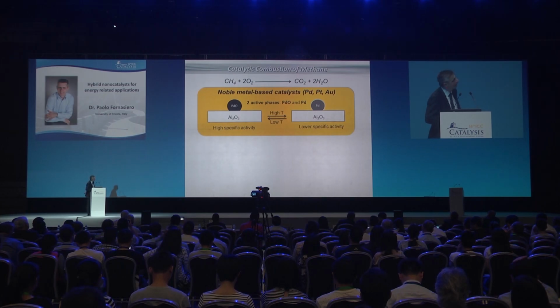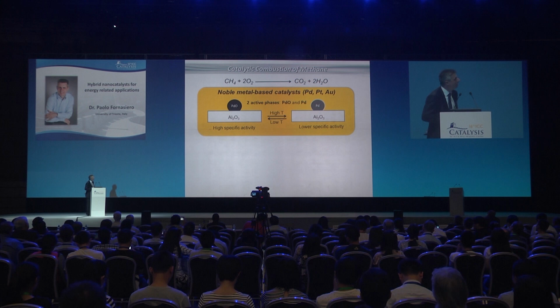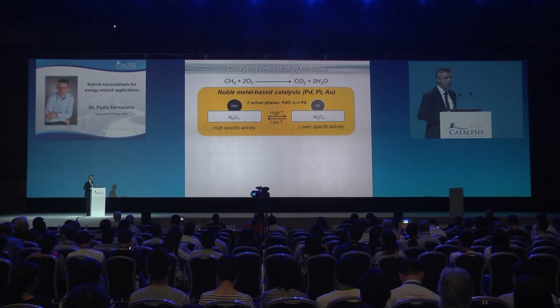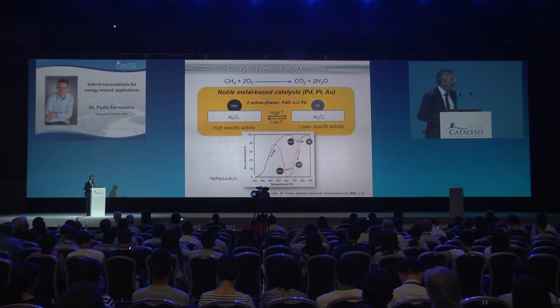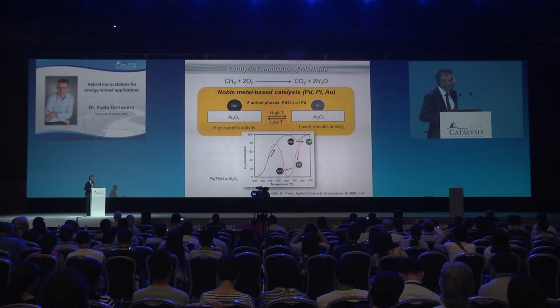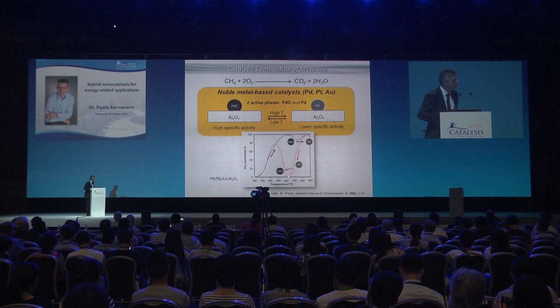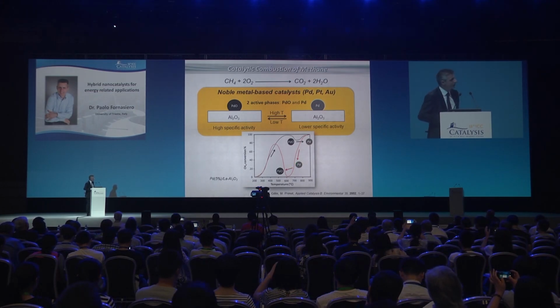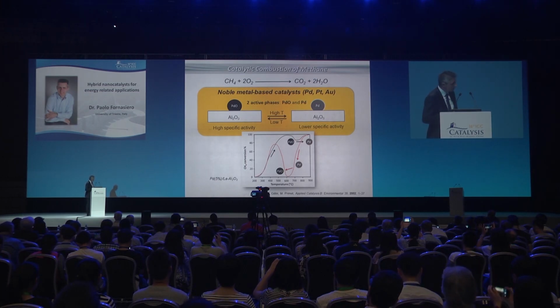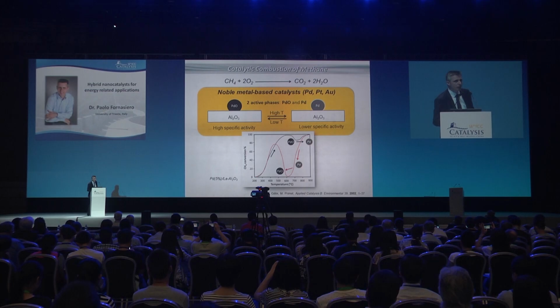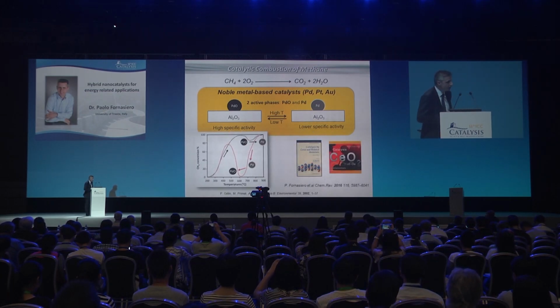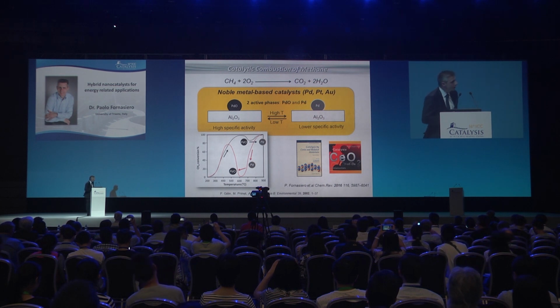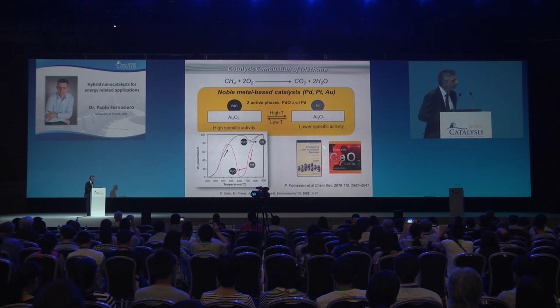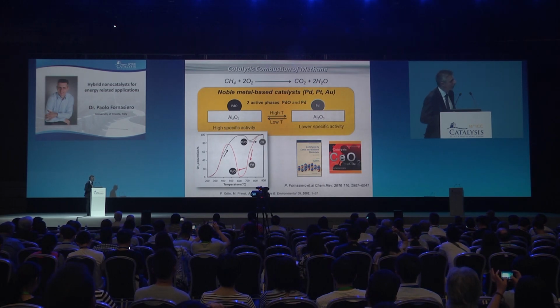So the most active catalyst for methane oxidation is palladium oxide. Unfortunately, when you go up in the temperature, palladium oxide decomposes to palladium metal, which is not active. So this leads to deactivation of the catalyst due to the formation of palladium metal. And if you cool down the catalyst, it's quite difficult to be reoxidized from palladium metal due to kinetic limitations. So it's really important to keep palladium in an oxidized state, and cerium dioxide is really doing a great job in this respect, as you can read in this nice book published by Alessandro Trovarelli and myself a couple of years ago, or in this recent Chem Rev.